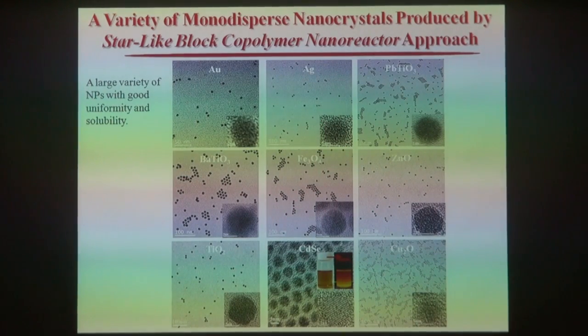So quite interestingly, this particular nanoreactor approach based on star-like copolymer is quite general. So in addition to ferroelectric titanate nanoparticles that I just demonstrated, we can also use this particular star-like copolymer to make a large variety of nanoparticles with very good uniformity and solubility, including metallic nanoparticles, they are silver and gold nanoparticles, and ferroelectric barium titanate. Here you see magnetic iron oxide. Here, this is the N-type zinc oxide nanoparticle, N-type titanium dioxide. Here you see luminescent cadmium selenide. It is orange emitting in this particular size. So the last one is the P-type semiconductor cuprous oxide.